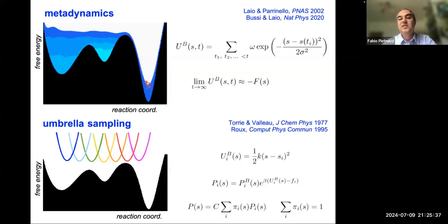One of them is metadynamics, just quickly, because maybe many of you know it, but it's not the topic of today. But metadynamics is a smart idea developed by Alessandro Laio and Michele Parrinello, where essentially you alter the local probability in the space of the reaction coordinate. So the local probability would be the exponential of the free energy. It's e to the minus beta F. Again, due to the barriers, you are trapped basically in the local minima for a very long time. But imagine now to fill the local minima. Imagine to alter the landscape by adding yourself some repulsive bias.